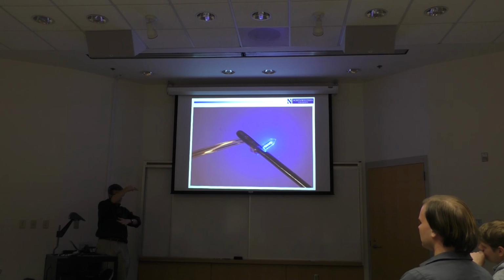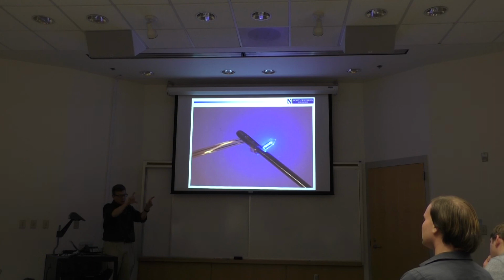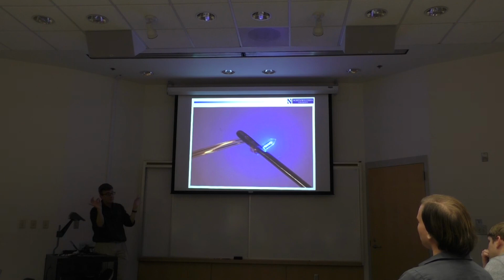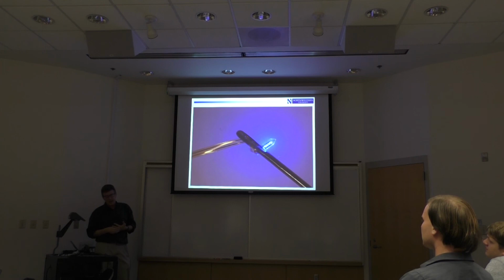And so we typically put the silicon in the neutral mechanical plane of the overall multi-layer stack. So when we bend our systems, the semiconductor layer is not seeing much in terms of strain anyway. And the ultimate bendability is not defined by the semiconductor layer, but the layers that are away from that neutral mechanical plane, like the gate dielectric or the interlayer dielectric or the thin film metallization that's doing the interconnect. So I think both of the things that you said are true, but they have very little impact on how you think about the system level design.